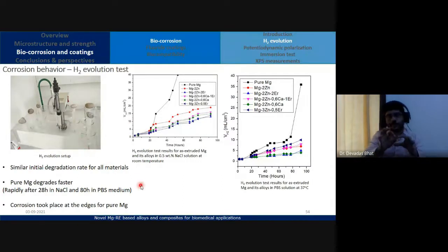You place your sample, you place an inverted flask, you place a test tube on that. Of course, the sample should be inside the corrosion medium. You create a water bath such that the water bath is at the temperature of 37 degrees Celsius. So you perform your test at 37.